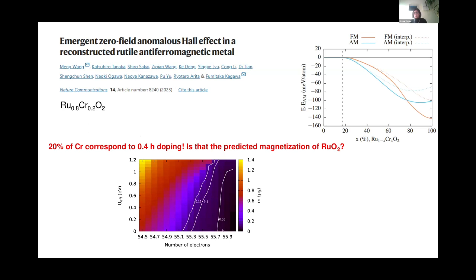So according to the calculations that we had, we would expect altermagnetic ordering. And these are, in fact, VCA calculations done by Andriy, where indeed if you have this doping and you look at the energies, you would expect at this doping the winning energy, so the magnetic ordering that is more stable, is an altermagnetic ordering. So this would fit in principle with these experiments, and we can discuss later on whether the experiments have some issues, but this would fit. However,